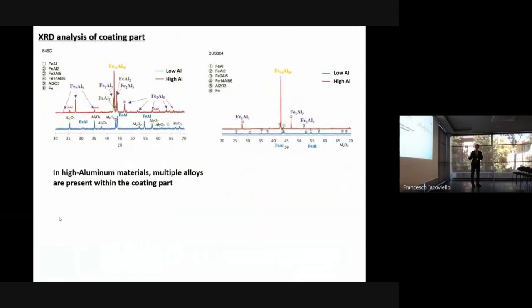Then this is the XRD analysis of the coating part. This is the S45C carbon steel. The blue line shows the low aluminum and the red shows the high aluminum content. In the low aluminum content material, only FeAl was detected by XRD analysis. In contrast, in the high aluminum content material, there are many kinds of FeAl alloys.